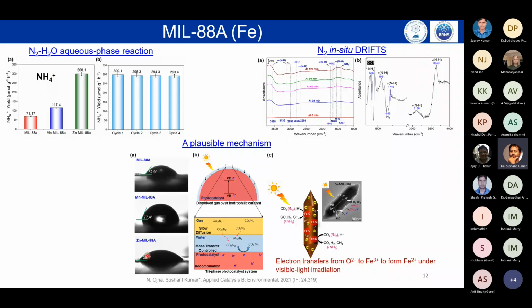Like you have a hydrophobic surface which should have more CO2, and then you have zinc, which is not so hydrophobic, but has a hydrophilic character. Now what we believe is that it has to have two things. One is not only hydrophobicity, or relative hydrophobicity, or more of a water contact angle, or a three phase reaction. You have to have very good optical and electronic properties to combine with, so that it can give you more product. Now that is happening only with the zinc and not with the manganese. Manganese was very close, but it was not the winner.